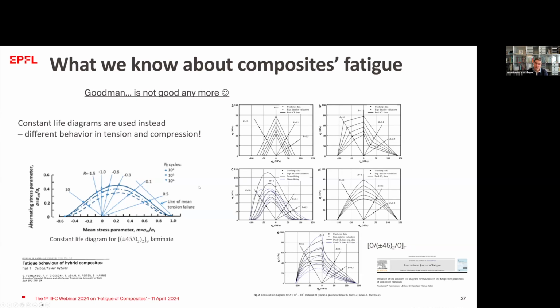But what I wanted to point out here is that these diagrams show also the difference of the material behavior in tension and compression. So depending on the material, it might be that the material is more susceptible to failure in tension or in compression, and we can collect this information by drawing these diagrams. We also have this information where, you remember, before we talked about fatigue and creep interaction. So when we reach R ratios that are close to 1, we have more creep components. When we are at R ratio minus 1, theoretically, we have only fatigue because there the mean stress is 0, actually.